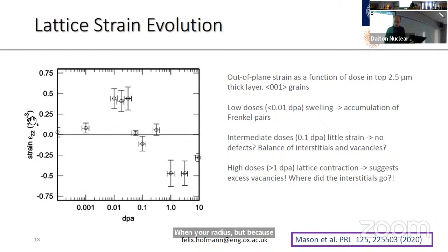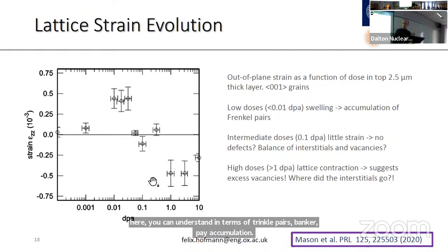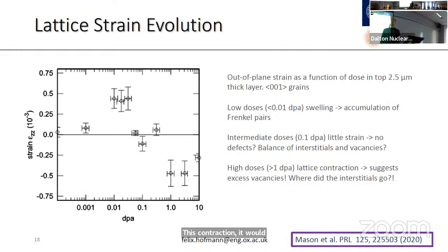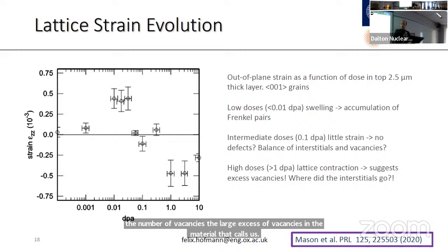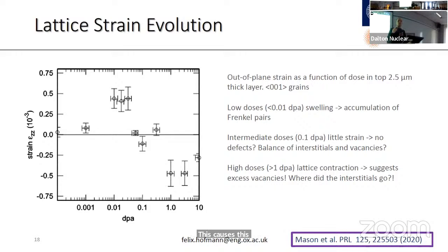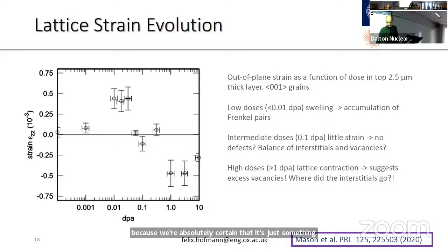Because lattice expansion you can understand in terms of Frenkel pair accumulation. This contraction would suggest that there's an enormous number of vacancies, a large excess of vacancies in the material that causes this contraction. And in fact, we were so convinced that this was wrong that we measured this twice, because we were absolutely certain there was something wrong with the experiment, but it came out exactly the same the second time.